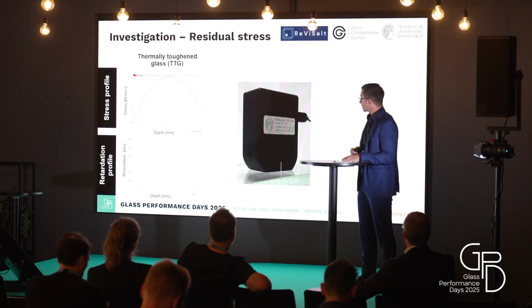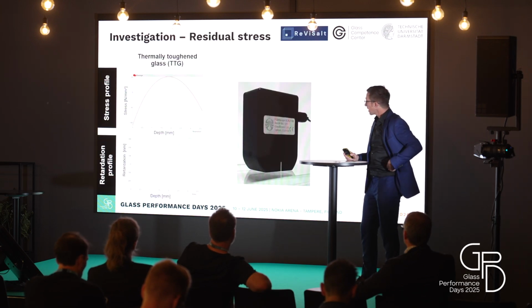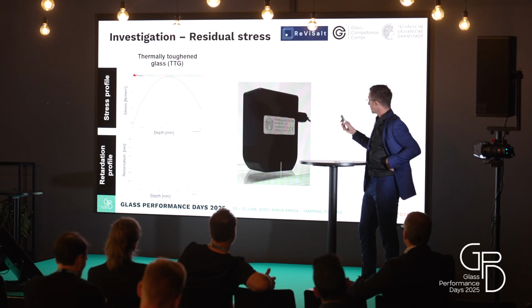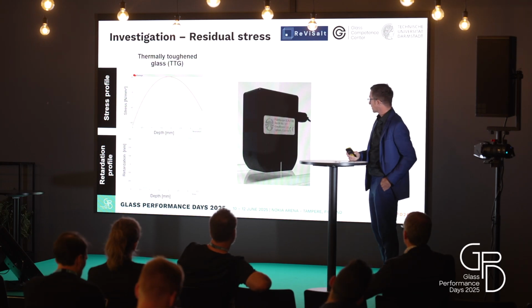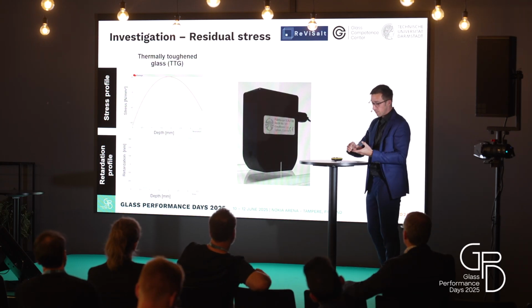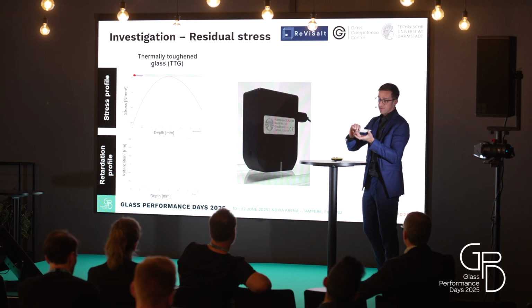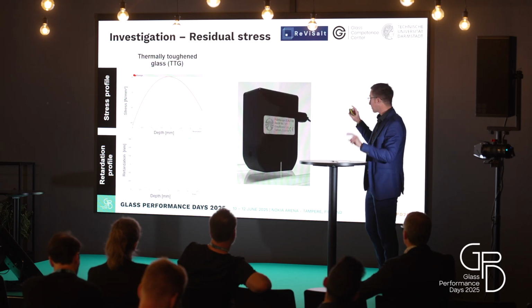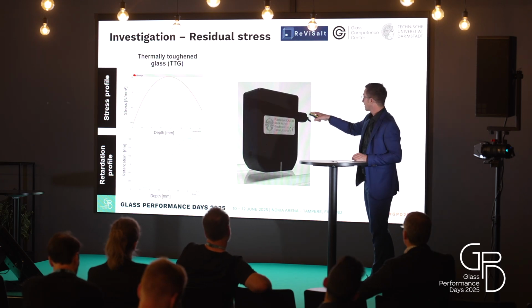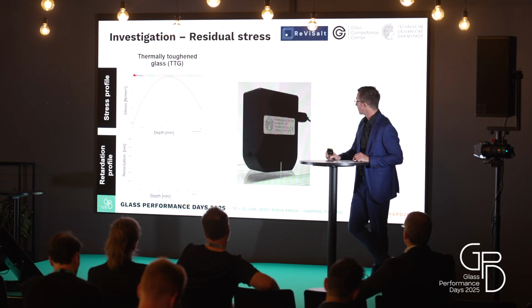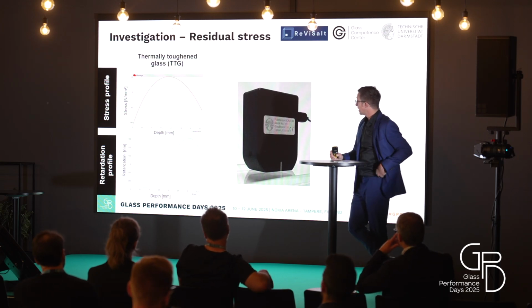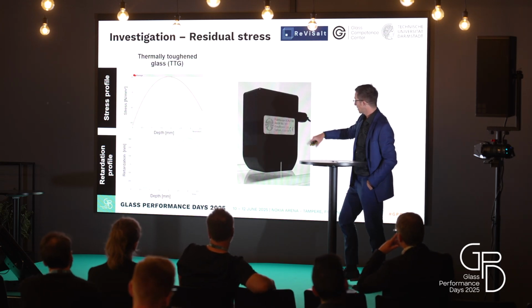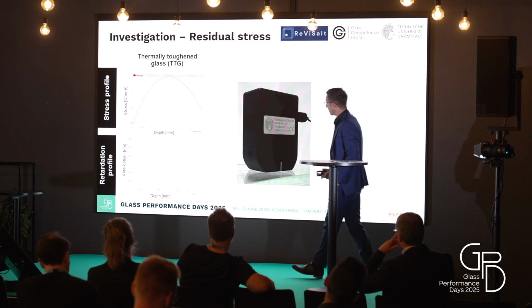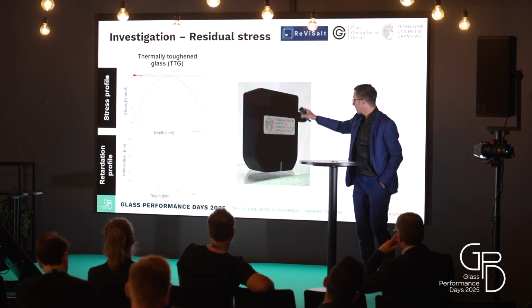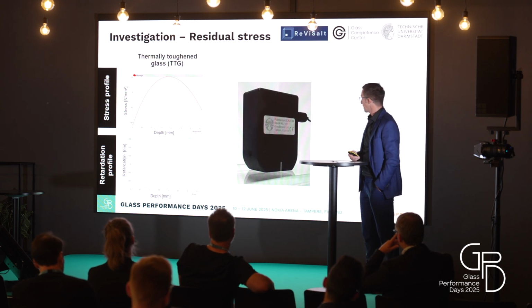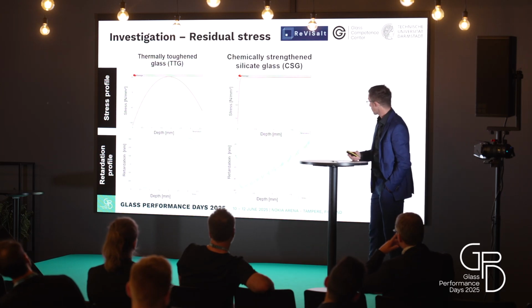Okay, let's talk about the results. Here you see we do some SCALP measurements. I think you know the device. We can measure with this device the stress profile over the thickness. It was pretty easy, more or less. This is a typical stress profile for fully tempered glass or thermally toughened glass, and this is the retardation profile you can see below there. These are the typical values. Here we are in the range over 100 megapascal or Newton per square millimeter.